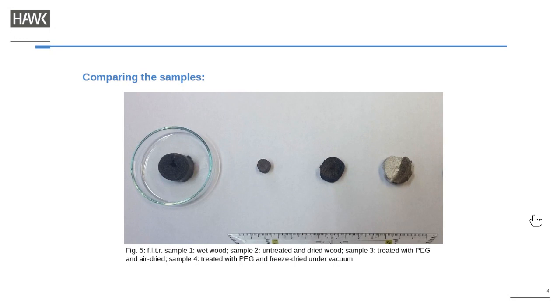The third sample is treated with PEG, but afterwards just air dried. So you can see the PEG already did a great deal, but quite a bit of shrinkage occurred. And the fourth sample is treated with PEG and then afterwards freeze dried. The white stuff on top is the crystallized PEG, which can just be cleaned off with a soft brush. And you can see that it's a bit lighter in color. It's quite light in weight as well. And the lighter color gives it a bit more of a natural finish.